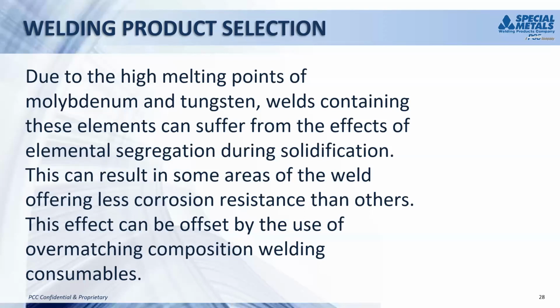Typically, stainless steels, the superaustenitic stainlesses, and some of the lower alloys like 904L have been welded with filler metal 625 or filler metal 622, both being overmatching in composition to the base metal. For the other nickel chrome alloys like alloys 22 and C276, we suggest the use of IncoWeld 686 CPT welding consumables. So in this case, even with elemental segregation, with our higher alloy content, you still get a weld that is matching or even overmatching the corrosion resistance of the base metal.